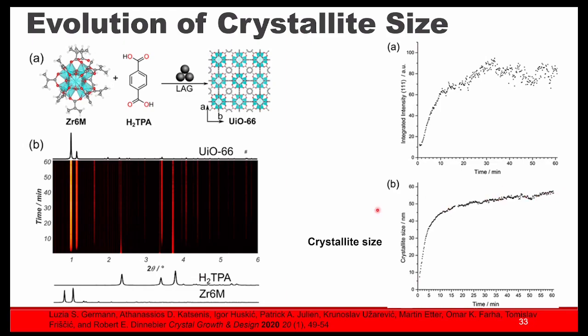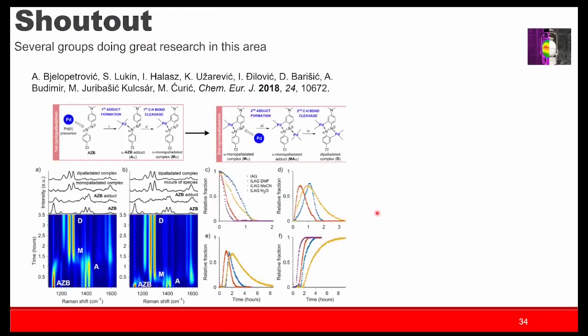So for liquid assisted grinding reactions, you don't actually have to worry that, oh, if I'm going to grind for an extra 30 minutes after the reaction is completed, you probably won't degrade the crystallinity of some of these harder materials, such as metal organic frameworks. So with this, this is the work that I presented.